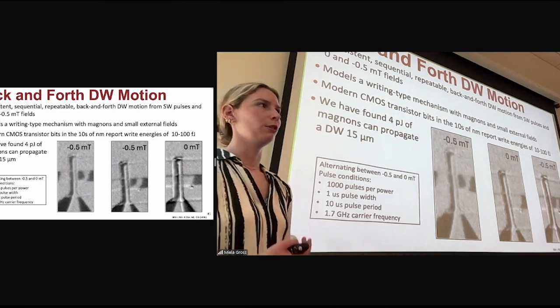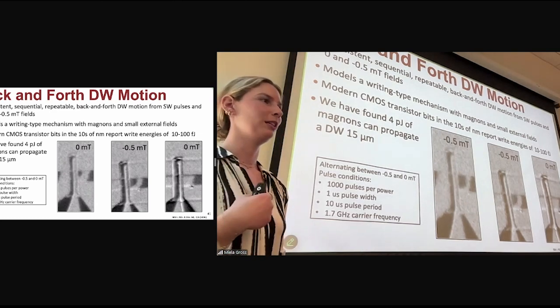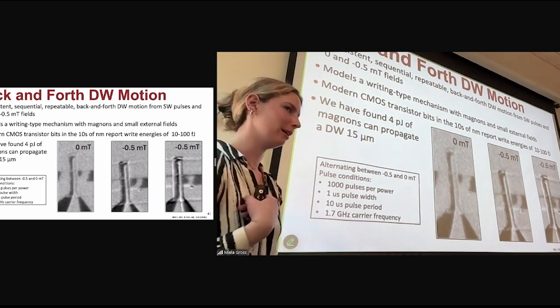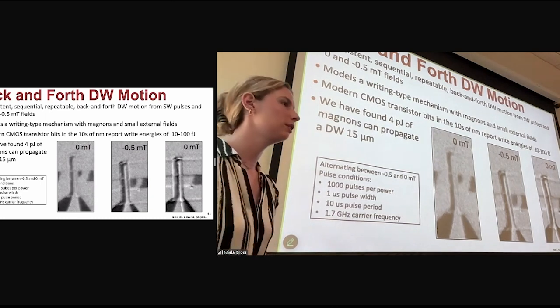However, if you remember previously, I was able to show domain wall motion of domain walls moving 15 microns with just 4 picojoules of spin wave energy.